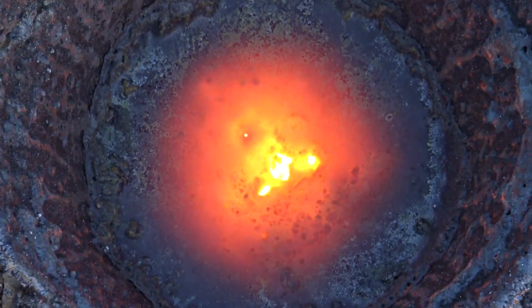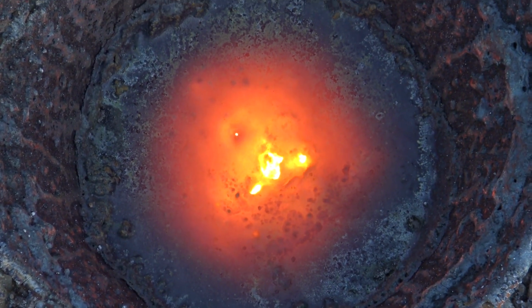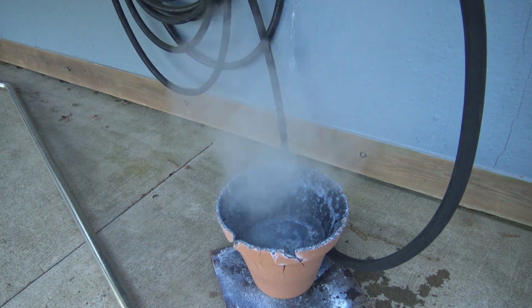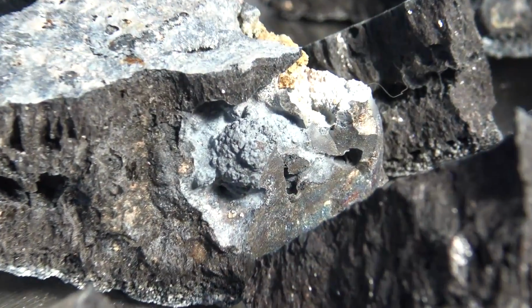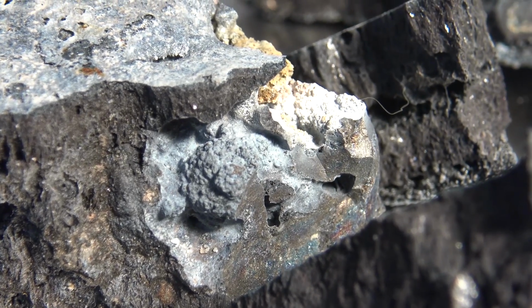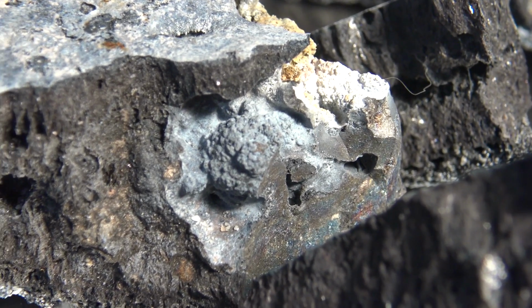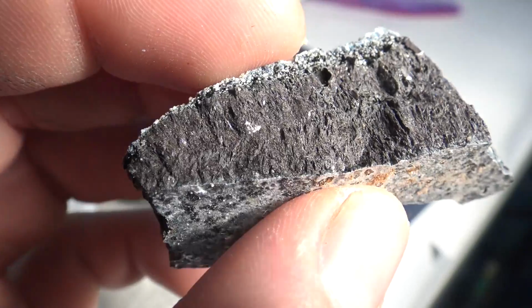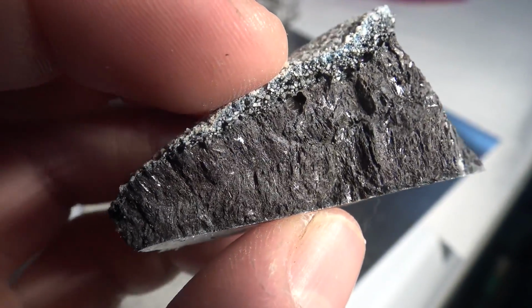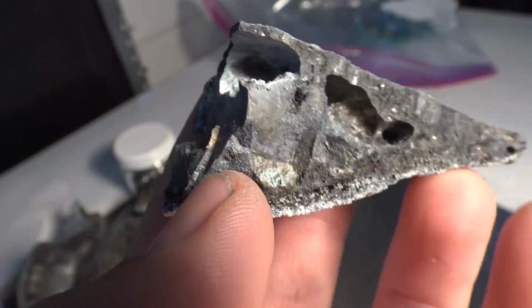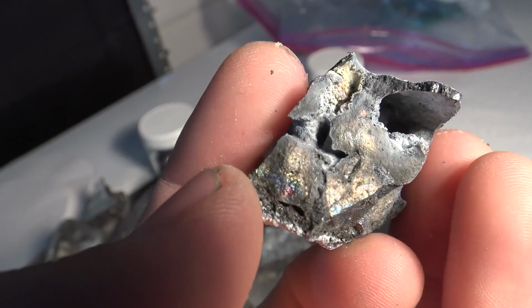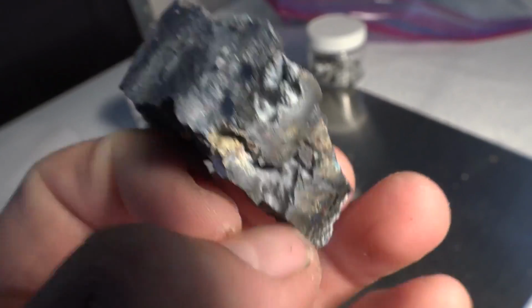After doing some thermite reaction, we can break it open, but unfortunately, because of the burst that occurred, the entire mass didn't have enough time to cool down and properly separate from the slag, most of which was thrown out of the pot, as you could probably tell. Not to worry though, as the components are cheap enough that we can just try it again, but this time we'll do an extraction of zirconium dioxide using the same formula along with the titanium.